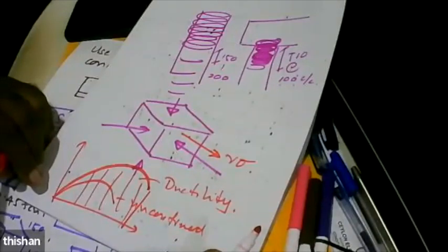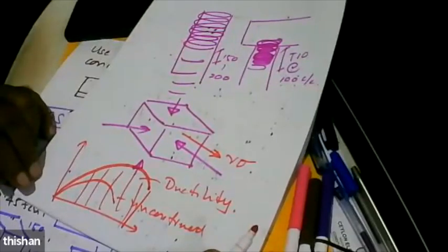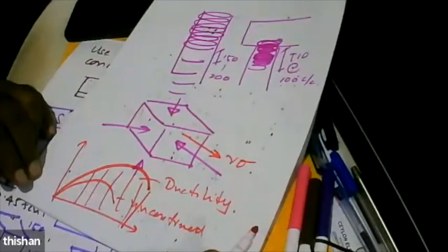so that it will not disintegrate easily. Because there's a huge strength in concrete when you have a three-dimensional stress state, like the way that you do triaxial tests in soil mechanics. Once you apply the stresses in all directions, all as compressive, then the compressive strength of the 30 megapascal concrete that you use will not be 30. It can be 40. And that comes not because the concrete is strong, but the confinement is high. So that's how we prevent earthquake damage on piles.